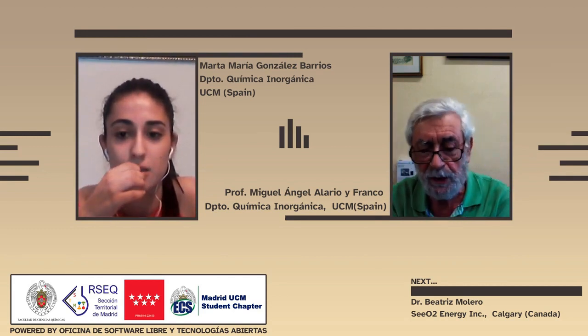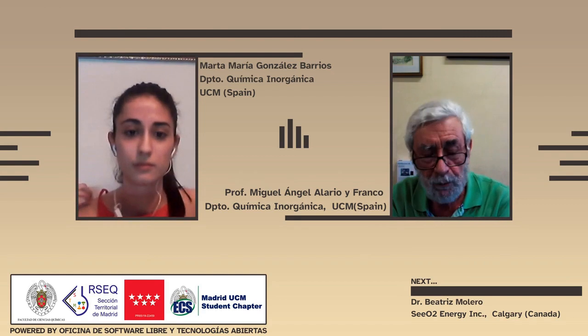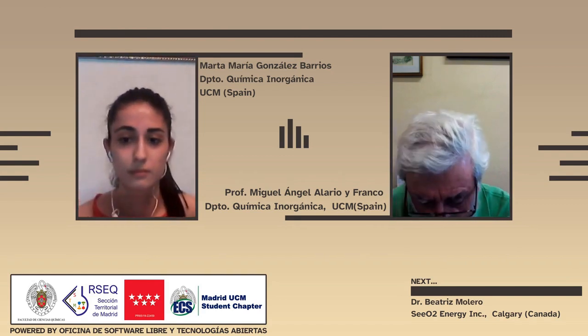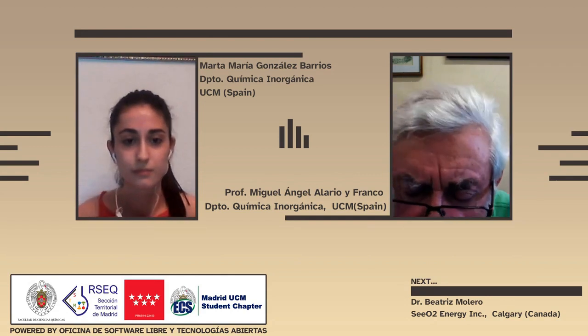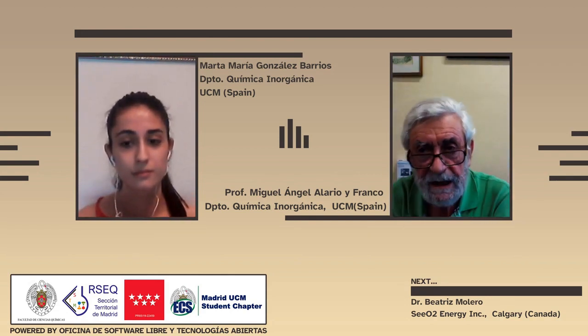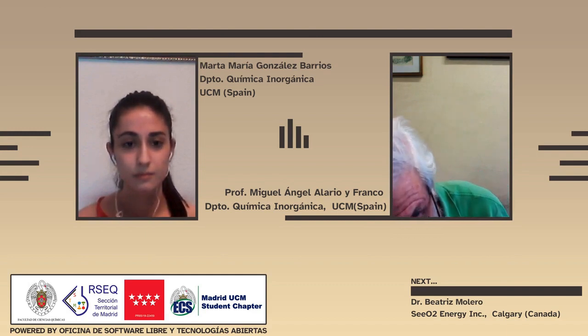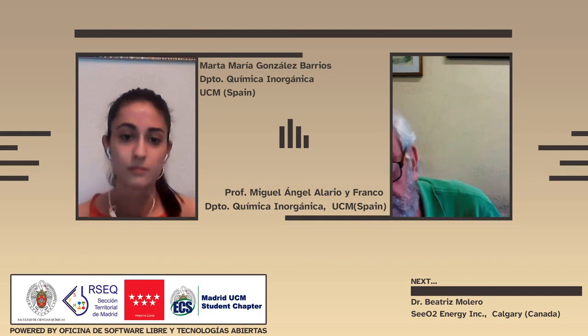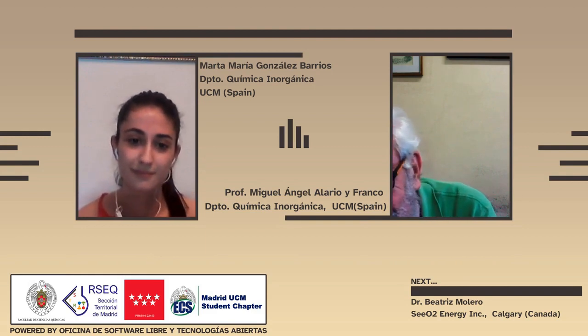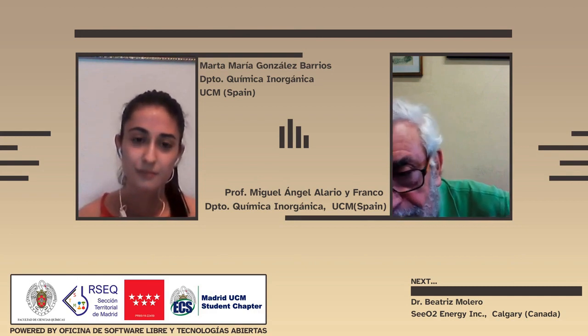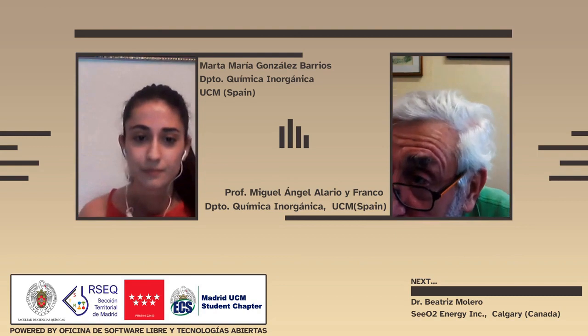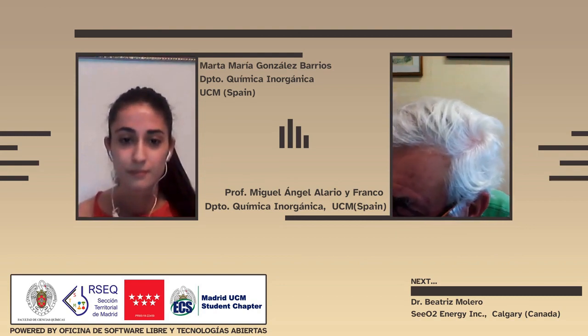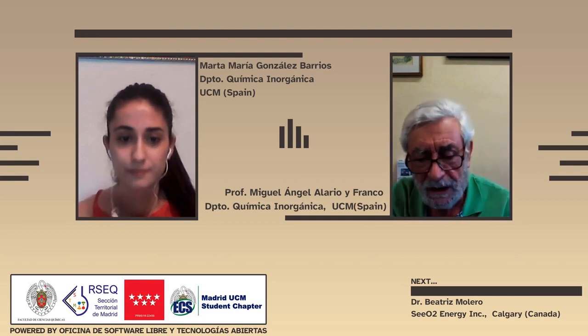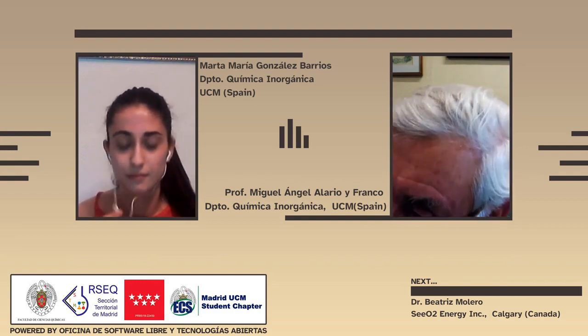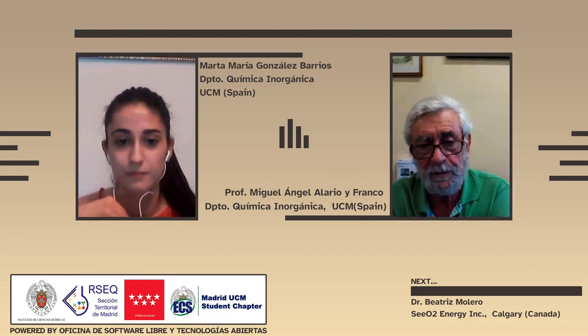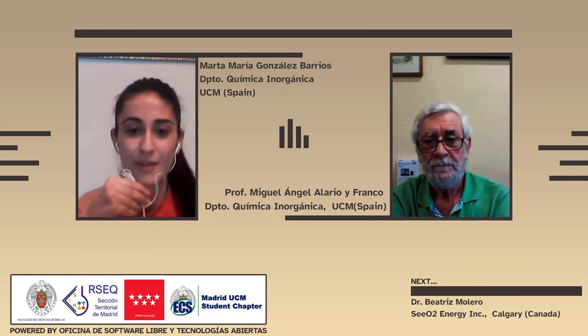Particle size, in principle, no. This is an atomic property. So we have actually worked with Maria Jose Torralbo and Veronica on the influence of particle size on the critical temperature. And if you decrease this particle size very much, you make nanoparticles, very small nanoparticles, then Tc disappears or decreases because the mean free path decreases. And then you finally end up not having a superconductor. So if the microstructure is really very small, you can actually destroy superconductivity. Okay, thank you. Thank you so much.